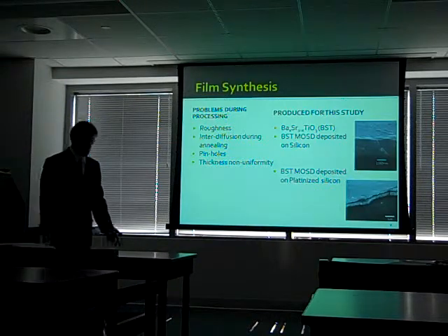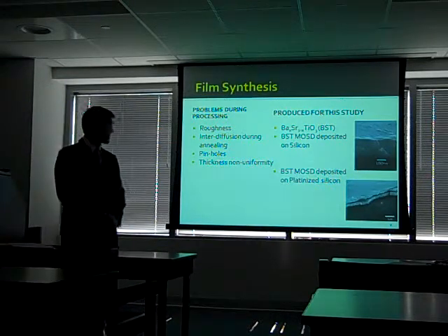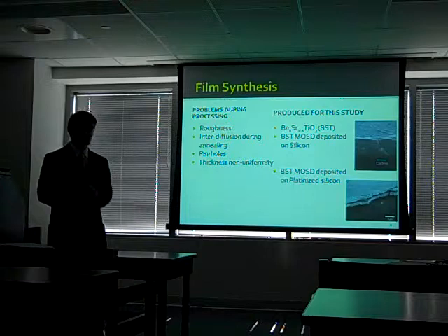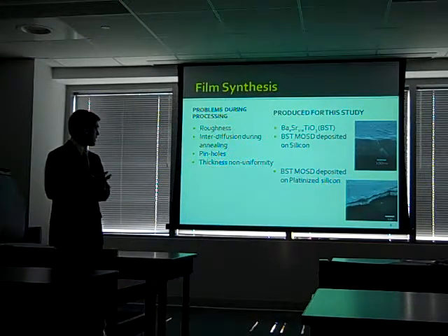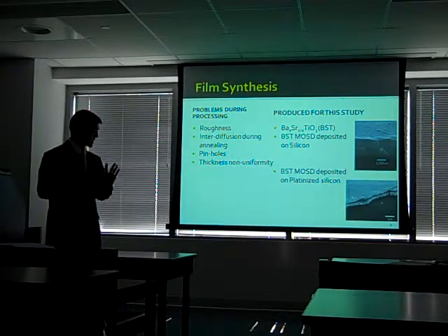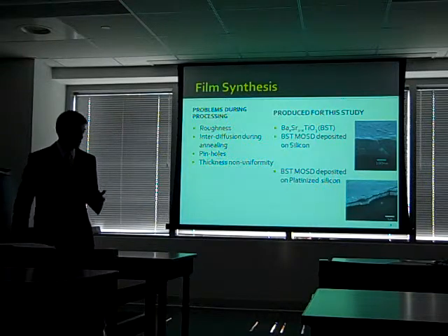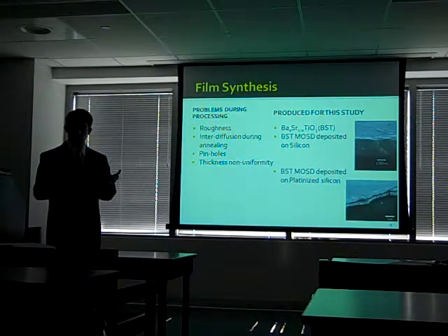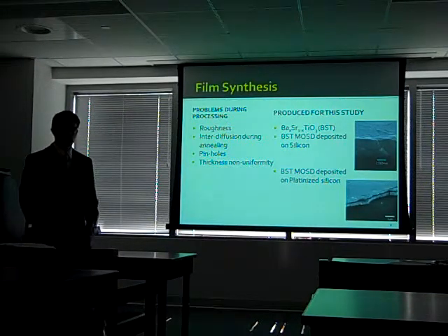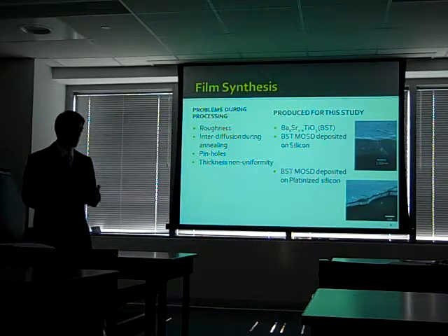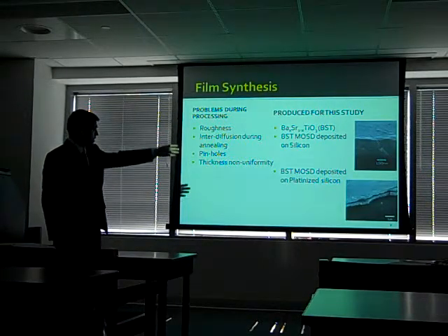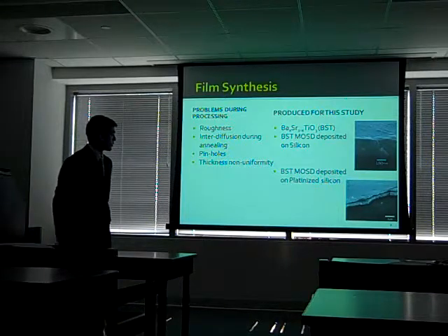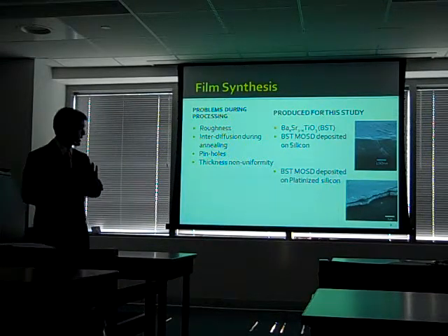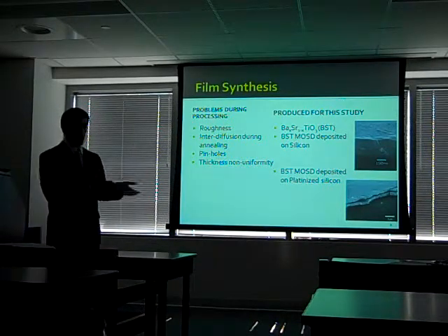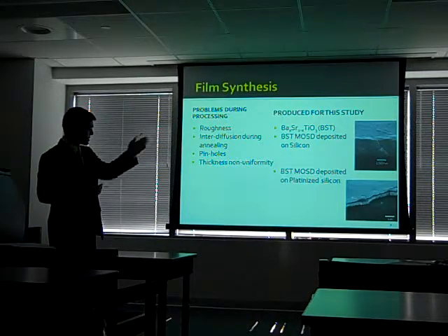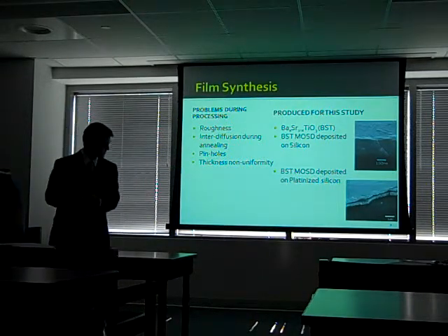But as you would expect, there can be problems during processing. Some typical problems with these techniques are film roughness, interdiffusion during annealing, and thickness non-uniformities. It's inherent with the processing, but we want to understand them and characterize them so that we can ensure high yield and good quality devices. Also, I wanted to mention that the films used in this study were produced by the MOSD technique on one of 2 different substrates. One is silicon and one is platinized silicon.